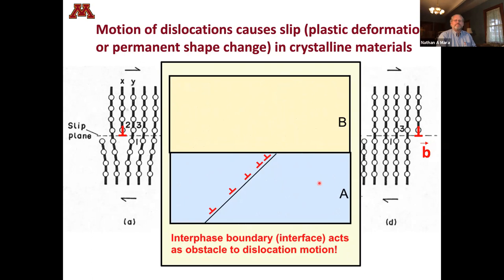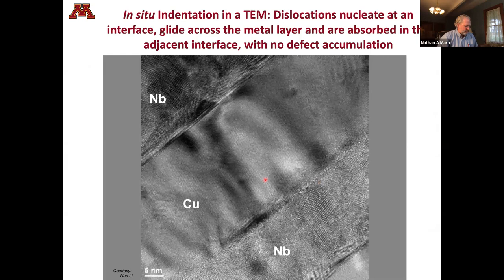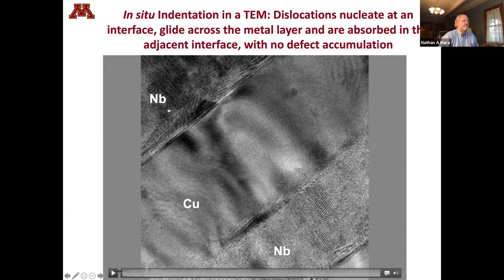So you don't have to take my word for this. They actually do exist. People have seen them in the electron microscope for about the last 70 years now. And so what we have here is an electron micrograph. It's high resolution, so you can see individual lattice planes. Hopefully you can see those there as well. And in this case, we've got alternating layers of niobium, copper, and niobium. And what we're gonna do is compress this material in the transmission electron microscope from the lower right-hand corner.